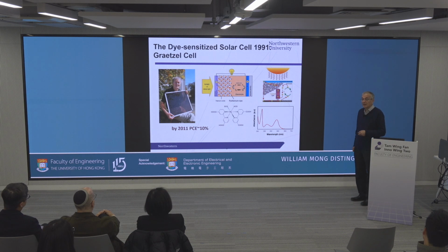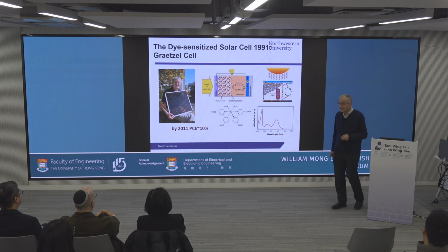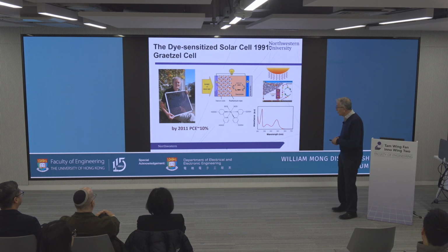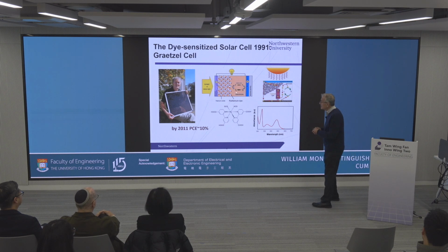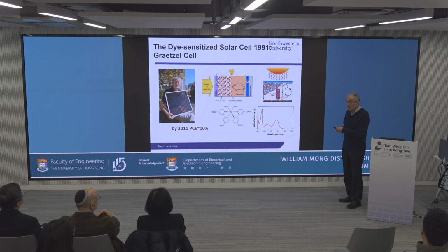Chemists were very impressed by this because it was working. And by 2011, it was up to 10%, 11%, which was, at that time, an impressive number. People were talking that if you can make it 13% or so, it would be commercialized, that kind of thing. But there was a problem. It was unstable. Because this is liquid, the solvent eventually takes this thing off the surface into the solution, and then it stops working. And also the solvent creates other problems with the layers, and it leaks out, and the stability was very poor.